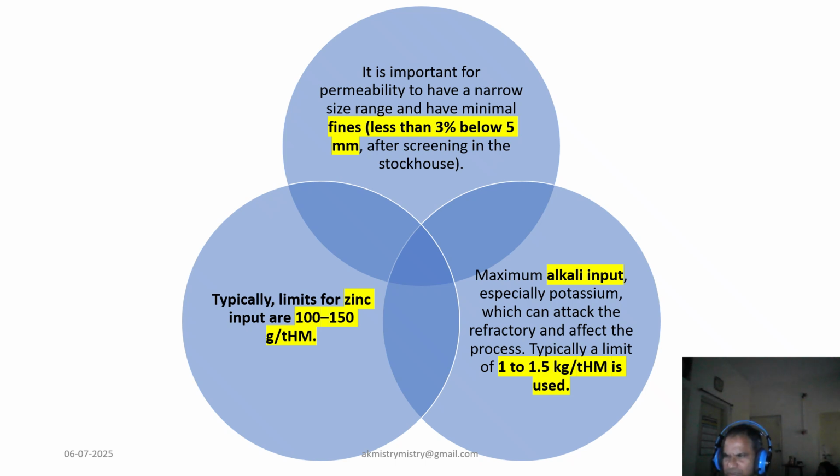to each other. As we must be knowing, if alkali input increases, then crumbling of coke will be higher, as well as we will have to top up more fuel, which also results in higher slag volume and lesser production. At the same time, crumbling of coke will lead to a permeability issue as well. Hence, maintaining a good permeability is really a huge enabler for running the furnaces in a better way.